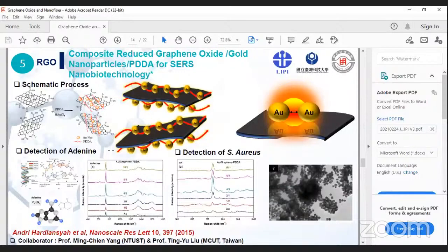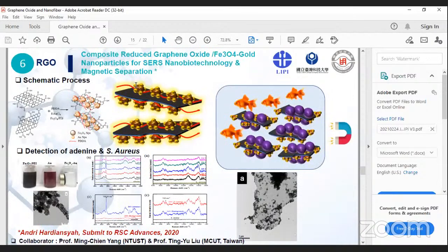And the second one is still in the development of SERS nanobiotechnology. We prepare the same graphene oxide and reduced graphene oxide, and then try to composite it with gold nanoparticles, because gold nanoparticles have a hotspot effect during the Raman spectroscopy, so we can get enhancement of the Raman signal, especially for adenine and S. aureus. Of course, the concentration of the nanocomposite has a very high influence on the detection of this adenine or the bacteria. And it is still the same for the SERS application.